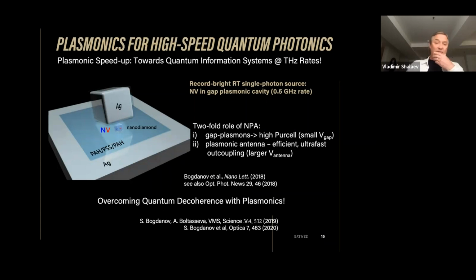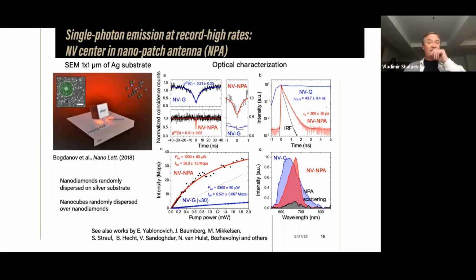So then ideally your system would operate in such a way that your photon would be emitted before decoherence happens, meaning that it would be immune to decoherence. And it could also be faster than any loss, meaning that your plasmons do not have enough time to decay. So it would be loss-free, decoherence-free outcoupling of single photons. And all calculations and preliminary results show that it's quite doable. You just need these very efficient plasmonic nanoantennas. So this is a first experiment. It was naive, but already very promising.